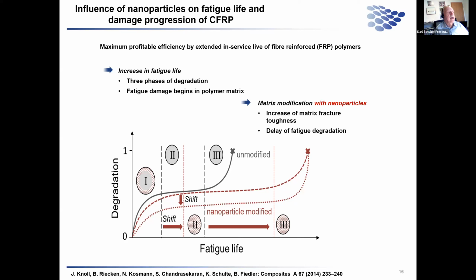If we now have the matrix modified with a nanomaterial, nanomodified, we see a shift as well, that the degradation is delayed. With this delay in degradation, we have also an increase in fatigue life before we have final failure.